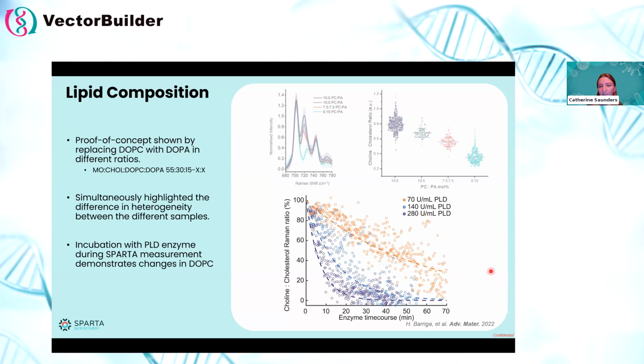So what you can then see is, each one of these dots again is an individual particle, but now the x-axis is looking at this over time. What you can see is that this interchange between the head groups was very dependent on the amount of enzyme that was added. As you'd imagine, the lower amount of enzyme led to slower kinetics, whereas with the higher amount of the enzyme you had a much shorter changeover. And so this led you to understand the influence of the enzyme, and also a bit of formulation tuning to really tune the kinetics of this changeover.